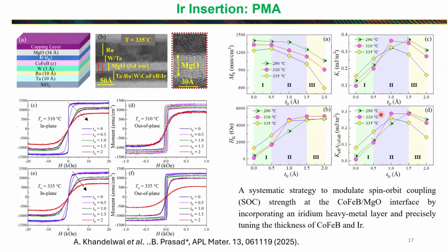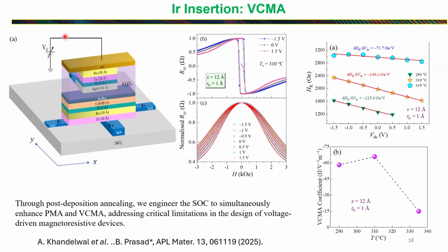So this is the PMA part. And then we also did the VCMA measurement. For that, we make a Hall device, and we measured the Hall resistance for different gate voltages. We apply the gate voltage across this, measure the Hall resistance, and then extract this part where we apply the gate voltage from minus 1.5 volt to plus 1.5 volt. You can see how the resistance changes with the applied gate voltage, and you can fit with the Stoner-Wohlfarth model, and from that you get the HK versus the gate voltage, and then calculate the VCMA coefficient. So we got the highest VCMA coefficient for the stack annealed at 310 degrees centigrade with a higher PMA. That gives the conclusion that you need to find the right annealing temperature and the right insertion layer.